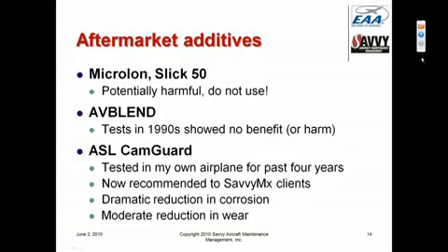So for a lot of our managed maintenance clients, we recommend what I use in my own airplane, which is plain Aeroshell W100 Plus monograde with the addition of a pint of CamGuard at every oil change, mainly for corrosion protection. It also, in my tests, showed a moderate reduction in wear metals in the oil analysis on the order of about 15%.